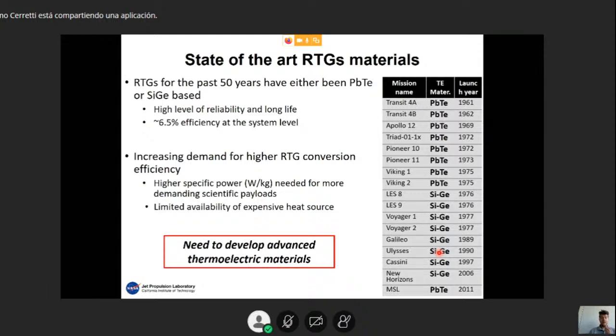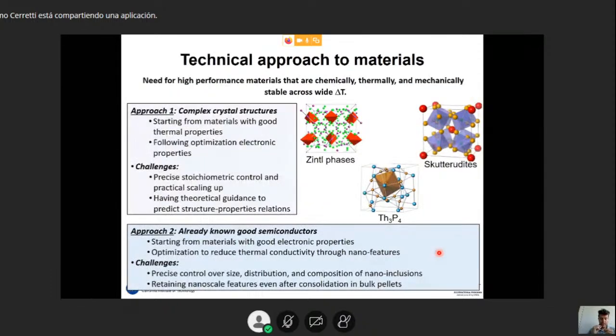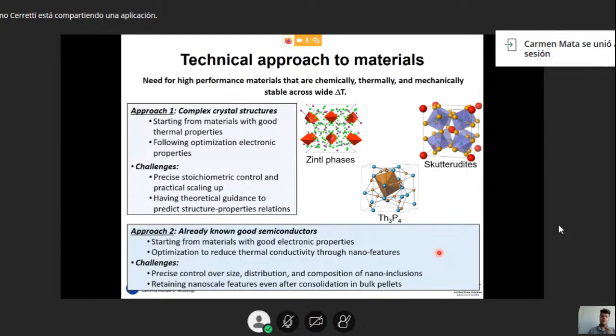Therefore, what we need to do is to develop more advanced thermoelectric materials. We basically use two main approaches to improve the thermoelectric material performances. The first approach is to start with materials that have complex crystal structures. The complex crystal structure ensures low thermal conductivity of the material, so the unit cell is formed by a lot of atoms, with a really weird disposition of atoms. These are all parameters that guarantee low thermal conductivity. And then from that, we start improving the electronic properties through some strategies like doping or compositing, as we will see further on.